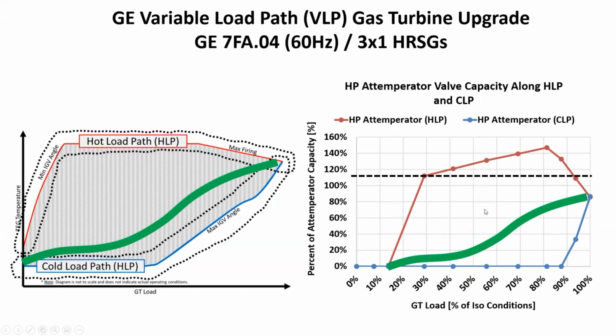Good. Okay. Are there other side effects or drawbacks, like environmental or anything emission based in that? Yeah, there are. I have a presentation that I could share with you after the fact, where the difference between the hot and the cold load path changes where the heat absorption of the HRSG is primarily. The cold load path shifts a lot of heat absorption to the IP and the LP system, and that actually causes more issues with capacity and pressure in the IP and LP system, whereas it doesn't affect the HP system as much. The hot load path, you can assume is similar to a gas turbine low load instance, where there are low exhaust gas flow rates but very high temperatures.